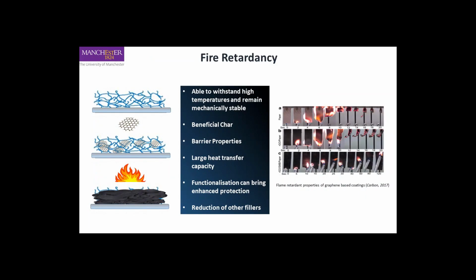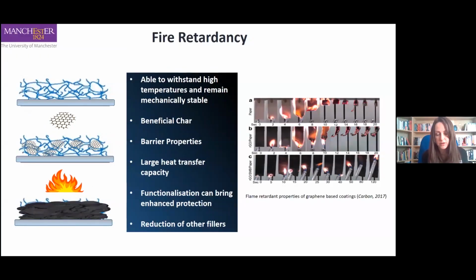The next application I'll talk about is fire retardant coatings. Carbon materials are already used in fire retardant coatings, graphite, carbon nanotubes, but people are obviously looking into graphene now to see whether that can improve on the properties. One of the benefits of using graphene is loading levels. If you're using traditional inorganic fillers within a fire retardant polymeric coating, you have to use lots of it, very high dose levels, and you can potentially use graphene instead and use much lower levels.